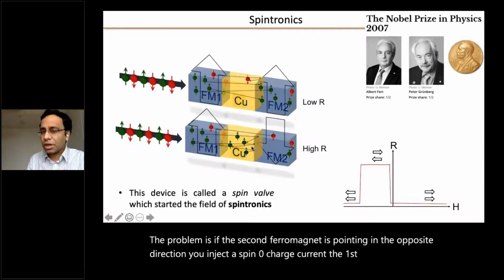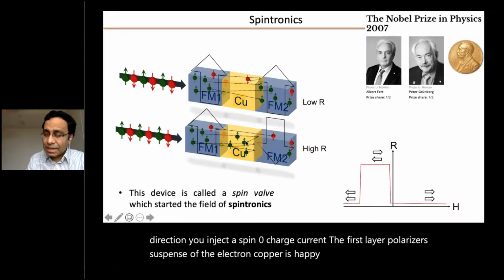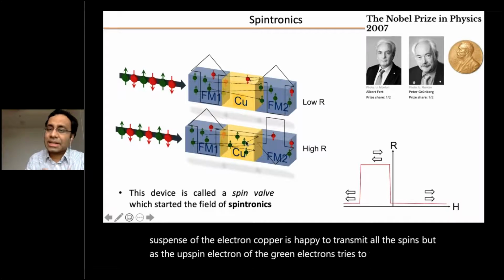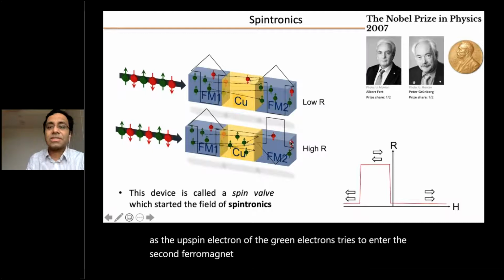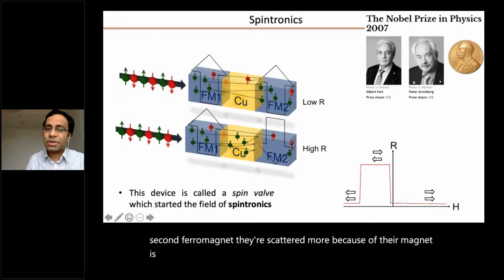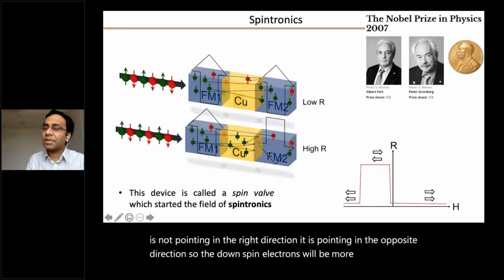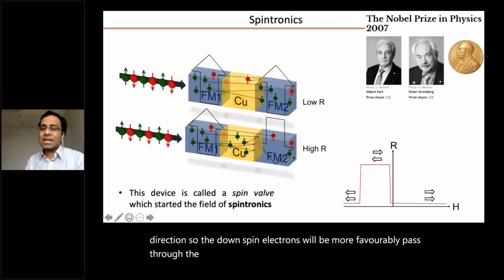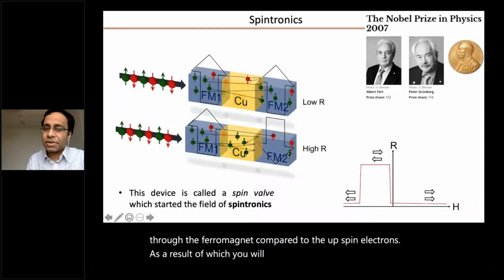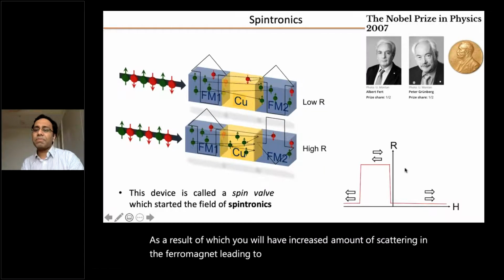The first layer polarizes the spins of the electrons. Copper is happy to transmit all the spins, but as the upspin electrons, the green electrons, try to enter the second ferromagnet, they are scattered more because the ferromagnet is pointing in the opposite direction. The downspin electrons will be more favorably passed through the ferromagnet compared to the upspin electrons, as a result of which you will have increased scattering in the ferromagnet, leading to a high resistance state of this device.